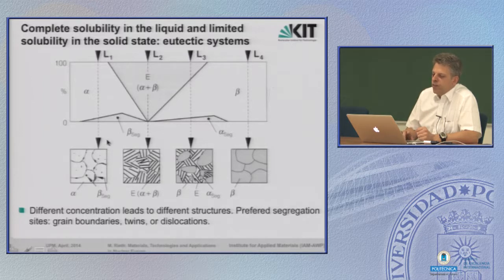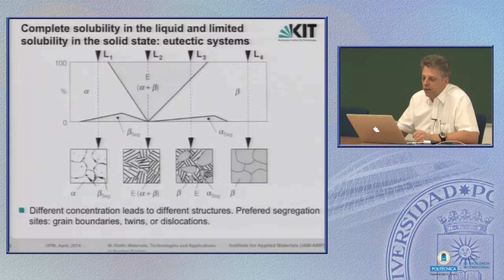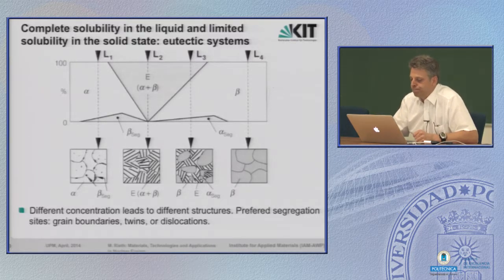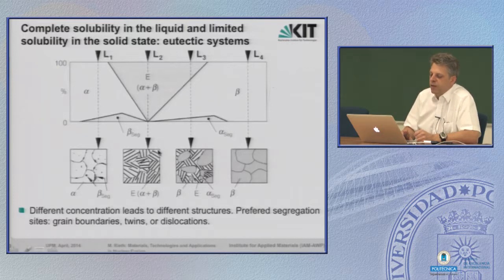If you have such a composition, which could be used as a precipitation hardened alloy, then you have the grains which consist of this alpha solid solute, that's the crystal, and inside the grains, but preferably along grain boundaries or also again along dislocations, these precipitates of the second phase form. In between, where we have eutectic or near eutectic compositions, first the grain forms during cooling down, and then inside the grains the eutectic structure forms.